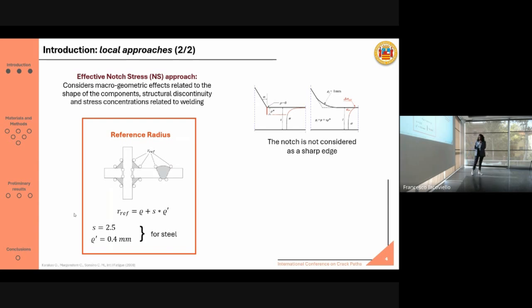In this case, the notch is not considered as a sharp edge, but as a blunt notch. So we introduce a reference radius that's even called the fictitious radius. Here you can see its expression that is available in literature. It's quite commonly used. And for steel, here we have the parameters that are usually used, but in general, this reference radius is of about 1 millimeter.